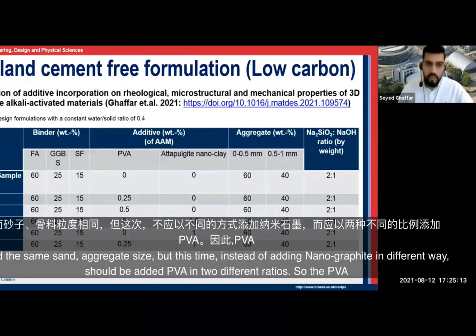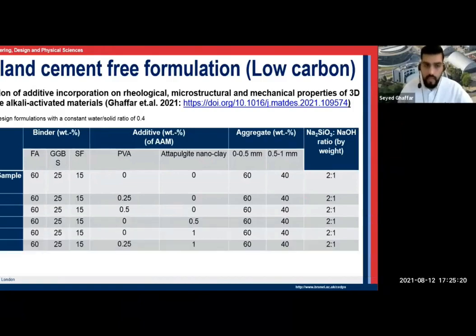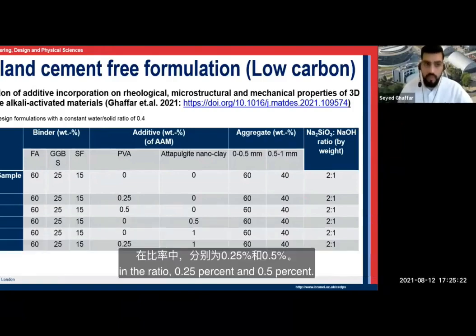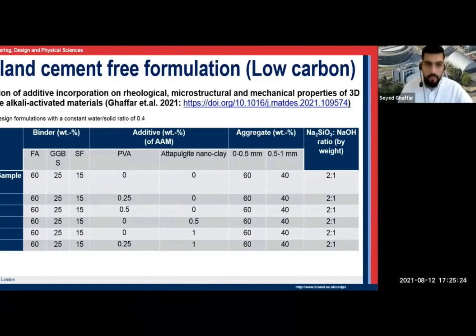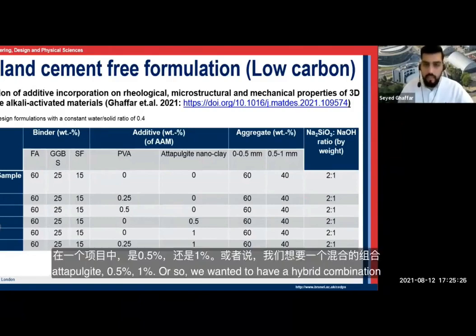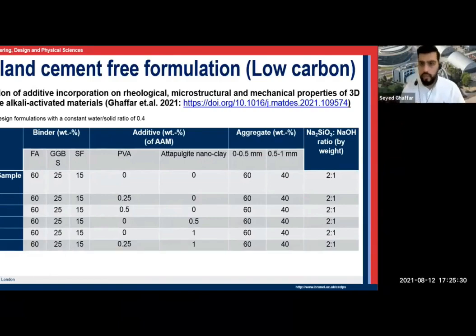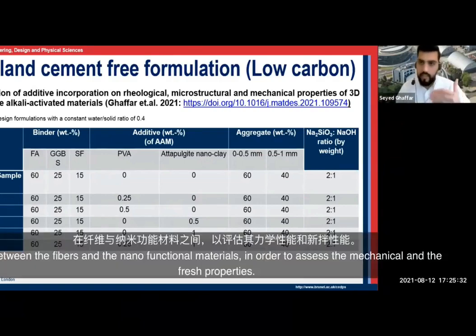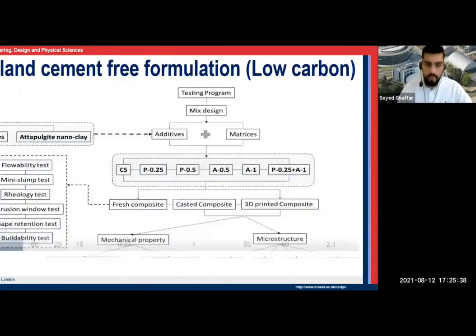But this time, instead of adding nanographite in different ratios, we added PVA fiber in two different ratios, 0.25% and 0.5%, and attapulgite at 0.5% and 1%. And also we wanted to have a hybrid combination between the fibers and the nanoclay functional materials in order to assess the mechanical and the fresh properties.